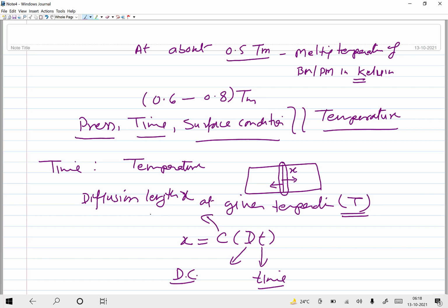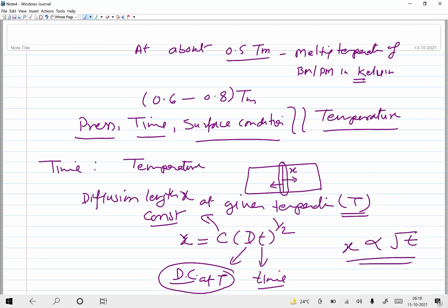This C is the constant. So diffusion coefficient at temperature capital T, at a given absolute temperature of the diffusion bonding, what will be the diffusion length? So if we see this simple equation, this average diffusion length is found proportional to the square root of the diffusion bonding time.